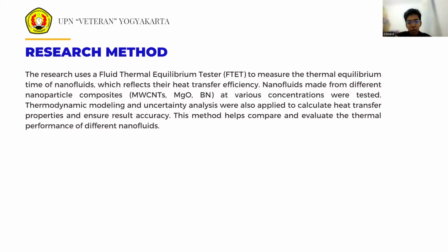Sonication was applied to prevent nanoparticle sedimentation and maintain uniform dispersion within the base fluid. Once the nanofluids were prepared, they were introduced to the FTET for testing. The procedure for each test involved filling cylinder A with the nanofluid and cylinder B with boiling distilled water. The system was sealed and temperature was monitored until thermal equilibrium was achieved.